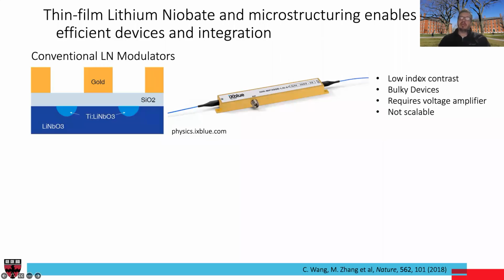Low index contrast in these types of devices also prevents us from making sharp turns and achieving high integration in this platform. Another issue is that, due to the epsilon of lithium niobate being quite large, microwave signals typically propagate much slower than optical signals, so phase and group velocity matching in this structure is challenging. This is why people often introduce an additional spacer layer of silicon dioxide to match these group and phase velocities, which in turn results in even worse electro-optic efficiency of this process.